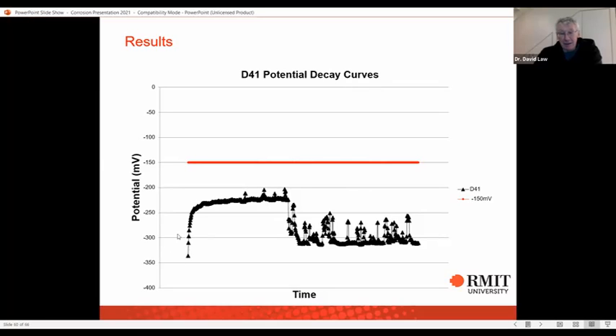Here, however, is the sort of thing where we would say we've lost our residual protection. You can see it moves up, and then for a period of time it's still maintaining that. So this is where we would say it's near passive. It's not managed to achieve the minus 150, but it's been drifting up and happily maintaining that upward drift. And then we suddenly get this drop, back down to a much lower potential again. This would indicate where we've lost that residual protection. So we think we maintained the residual protection when we switched off, for a period of time, but in this beam, which is D41, we've actually lost that protection over time. We're saying we've not achieved the minus 150, so it doesn't pass by what the standard would say, but we think we're still maintaining passivity here, and then we lose it.